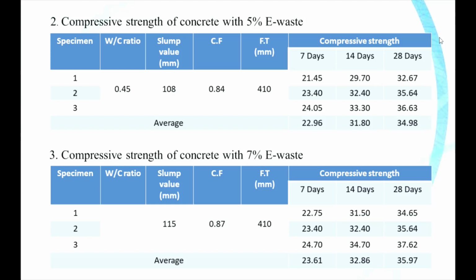So the average strength at 7 days is 23.61 megapascal. At 14 days there is a strength of 32.86 megapascal. At 28 days there is a strength of 35.97 megapascal. So as we compared it with the previous table, there is an increase in the strength.